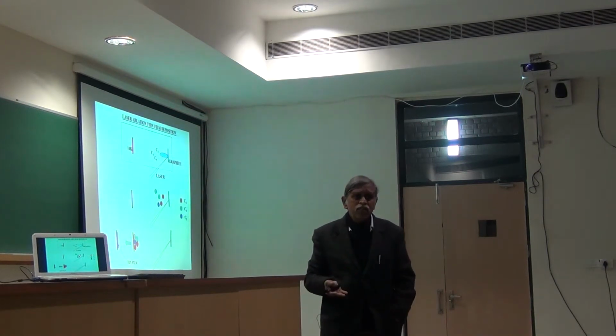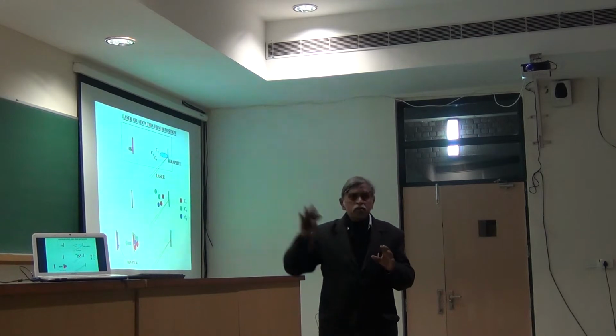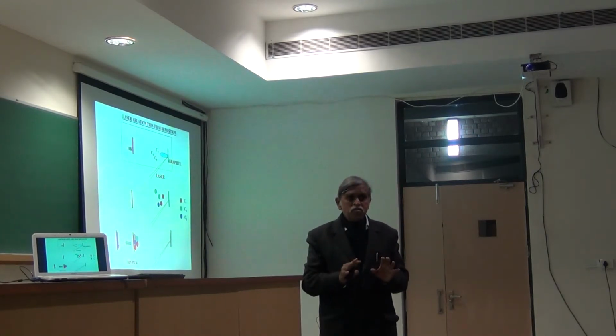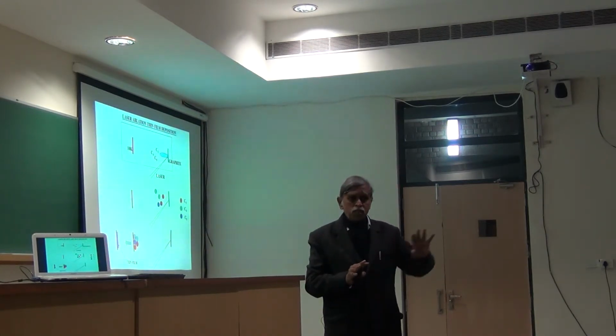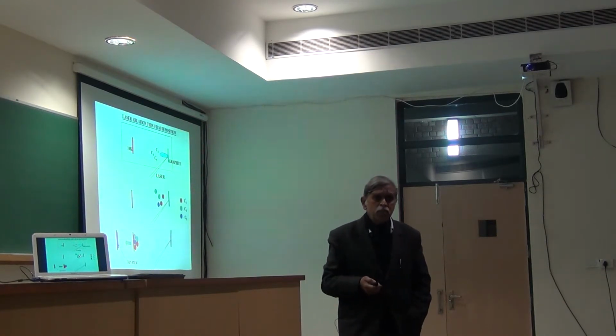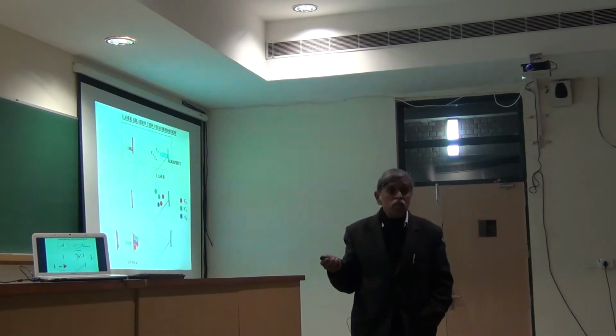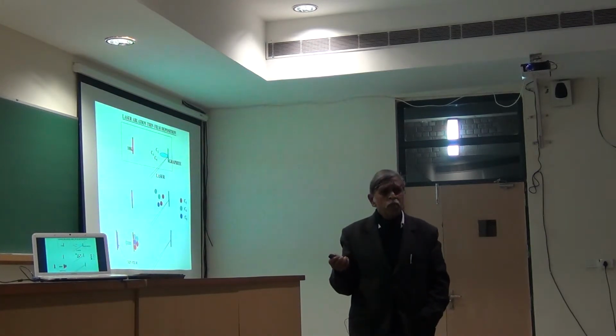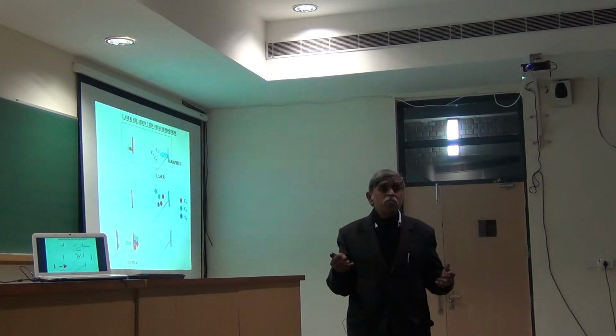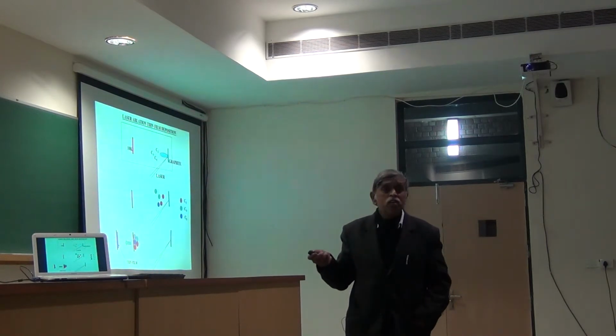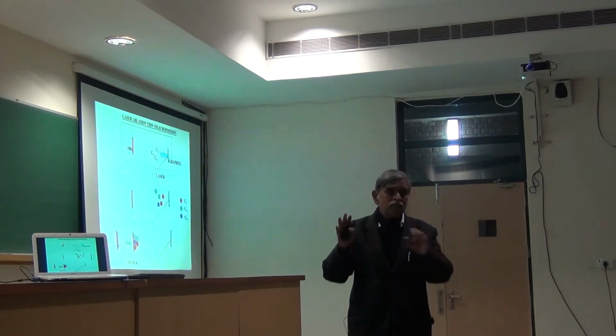At 10 Kelvin, I don't have the temperature to be able to do that. So all these are stable species in their ground states, and once they are there, they will be trapped in the structure that they have produced. If they were so unstable that they would have to dissociate, they would probably dissociate right here, because there's a certain time that it takes to go from here to here, which could be on the order of a few microseconds. So if they had lifetimes less than microseconds, then of course they would dissociate right here. But if they survive that, then they're...